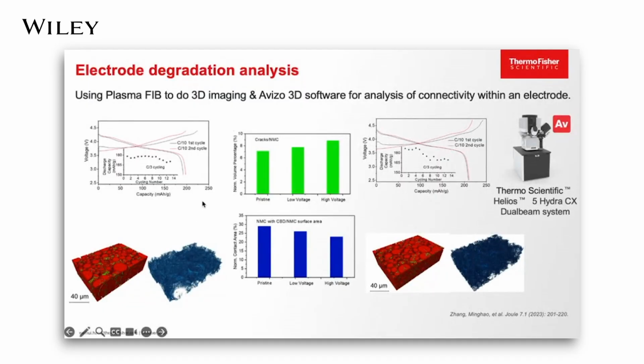If you look at this use case, it shows that a battery cycled at a higher voltage experienced heavier capacity degradation than at lower voltage, particularly in cells with thick electrodes. The degradation process in a thick electrode is closely associated with structural and chemical complexities at different length scales. Evaluating these complexities requires full 3D characterization. In this case, we use plasma focused ion beam to acquire a large 3D imaging volume of a thick electrode. This technology allows for high-resolution imaging and detailed analysis of the internal structure.